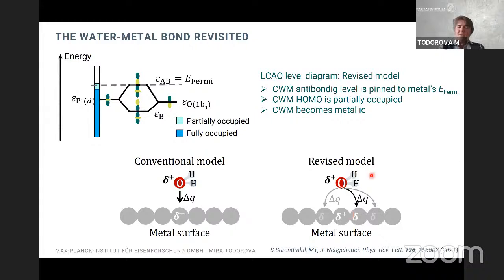We also have to revise our model a little bit, because what happens is that the chemisorbed water molecule anti-bonding level is pinned to the metal's Fermi energy. And this means also that the HOMO of this chemisorbed water molecule is partially occupied and it becomes metallic. And this means that it will have different properties in terms of screening. So our revised model for the bonding of the chemisorbed water molecule to the platinum surface is that not only the platinum atom directly below the water molecule is participating in this bonding, but also metal atoms around it.